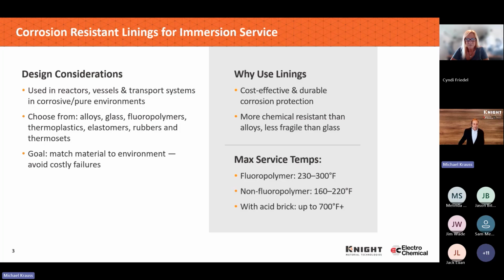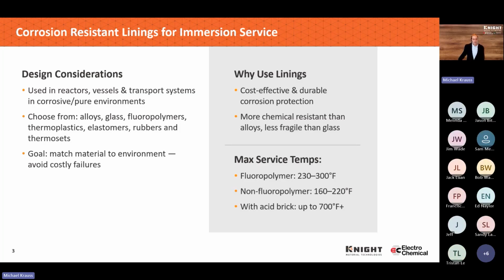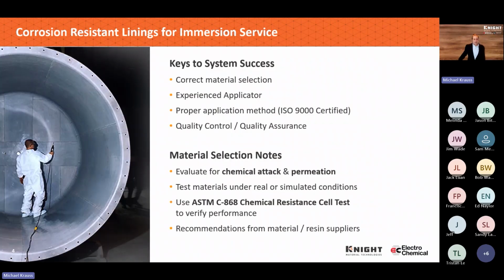Non-fluoropolymers a little bit lower, and we can actually improve it significantly by combining the Knight technology with the fluoropolymer lining and using the acid brick as a thermal barrier so that the process temperatures can see upwards of 700 degrees Fahrenheit, while the lining, providing the chemical resistance, is seeing a much lower temperature and providing a really robust and unique solution. When I look at the keys to success, I view it much like a table.